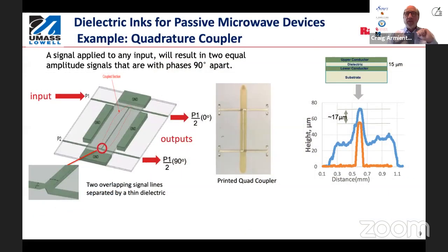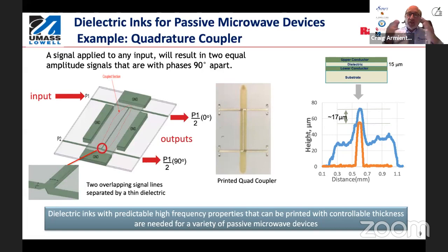Just to talk about one of those elements that speaks to the challenges for dielectrics. This is a quadrature coupler. You put an input on the left side, it gets split into two and shifted by a 90-degree phase. What's required is you've got these two metallic lines with a dielectric in between. You see a cross section here. The dielectric constant and that thickness have to be well known and controlled to be able to design and fabricate this with a set coupling. And that's a challenge right now: how do we get these dielectrics deposited in a way that's very controlled. And that's just one of the many challenges of dealing with some of these materials.